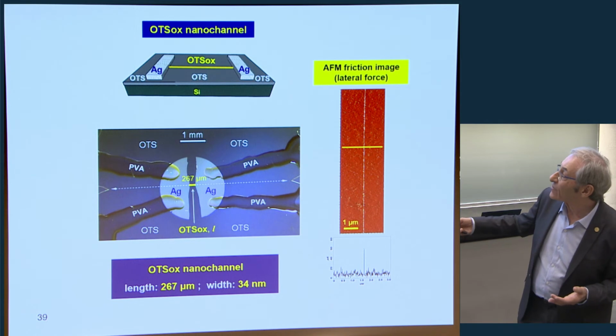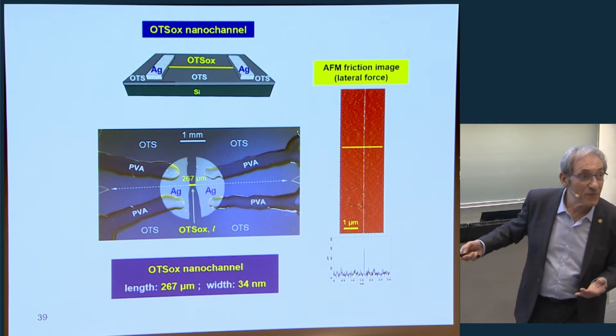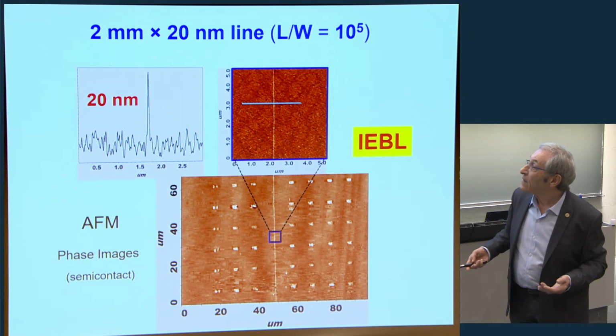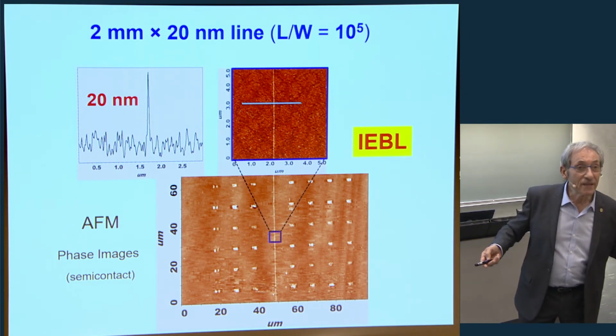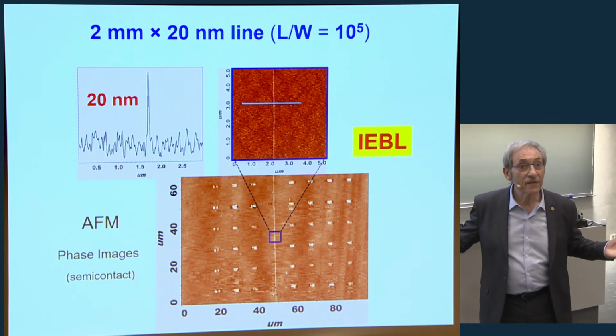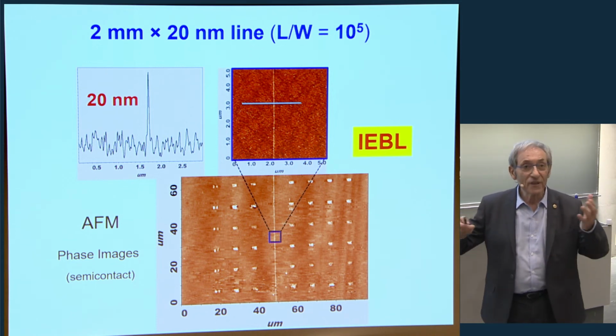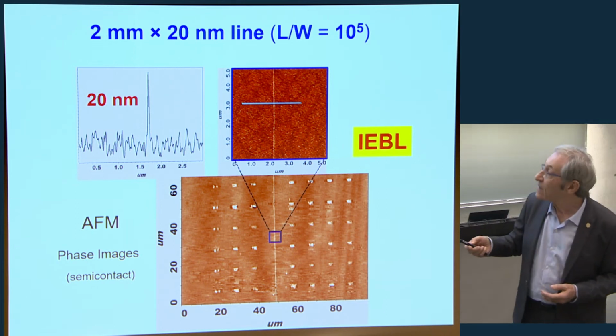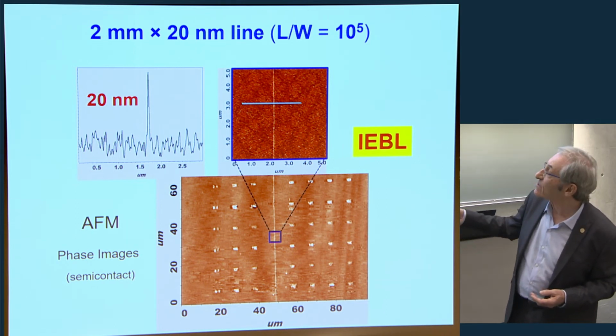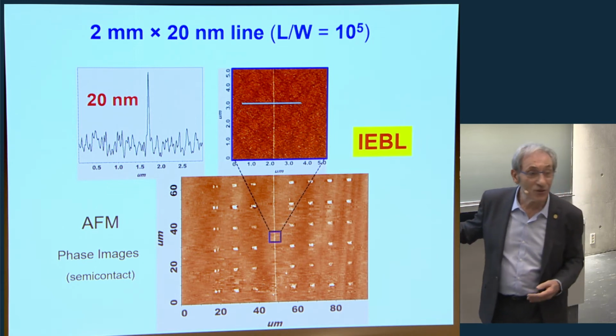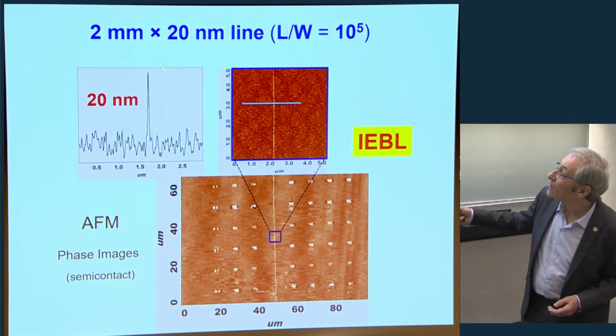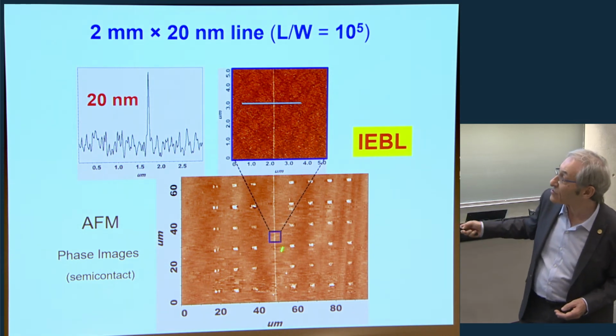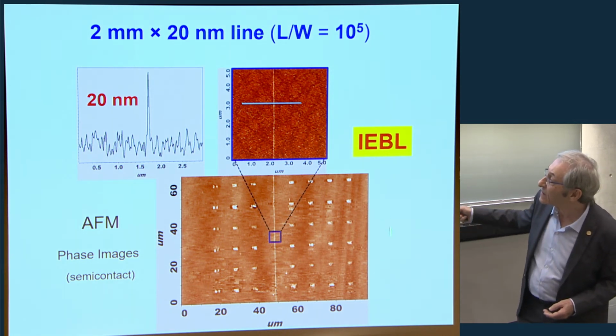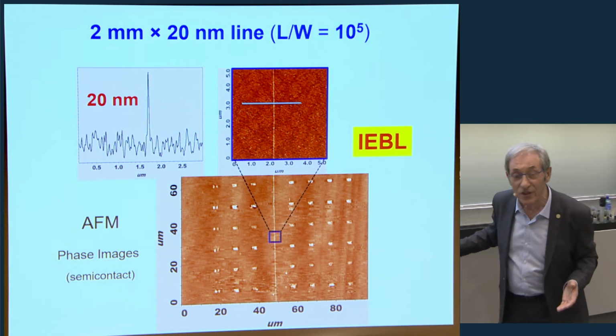Now, this is an AFM image of a portion of the line that you cannot see here. And now, with the electron beam, we can write extremely long lines, without the problems that we encounter with the AFM and the water and so on. So here you see IEBL, interfacial electron beam lithography. This is a line of 2 millimeters with a width of about 20 nanometers. And you see here the cross-section. And these are just markers in order to find the line on the surface.